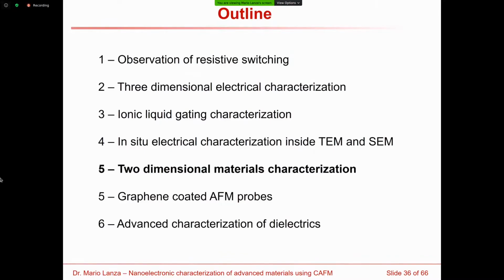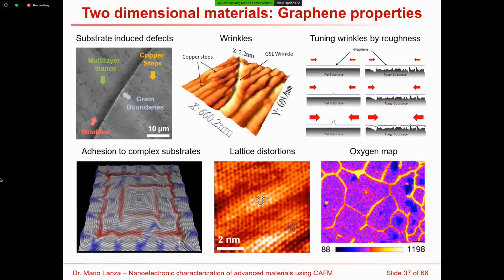Okay, in the next step, I wanted to share with you some other studies that we have done on two-dimensional materials characterization. So I started to work on graphene in 2010. That's the first 2D material that I analyzed, and I started to study it using most of the techniques that were used at that time, which is scanning electron microscopy, atomic force microscopy, scanning tunneling microscopy, also SEM and Auger electron spectroscopy. And we found something interesting. We were able to quantify the amount of wrinkles. We developed a method to reduce the amount of wrinkles by increasing the roughness of the substrate. And we also studied the passivation properties of graphene, the anti-corrosion and anti-oxidation properties of graphene when coating different types of metals.